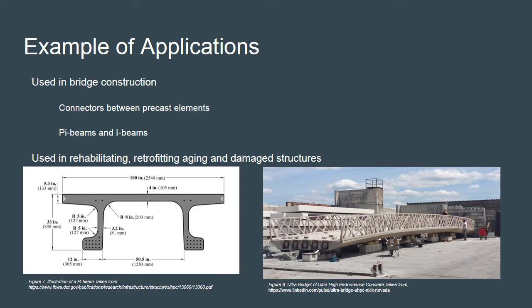The United States Federal Highway Administration released a report in 2011 detailing some of the uses of UHPC in the US. UHPC has already been used in several highway bridge construction projects. Two projects used UHPC in precast concrete girders in place of conventional concrete, where tensile properties were significant enough for the bridge to be designed without steel shear reinforcement. Two bridges in New York were built with UHPC acting as a connector between precast elements. Several pedestrian bridges around the world, including one in Sherbrooke, Quebec, have been built with UHPC slab decks. There are also wide-ranging applications in rehabilitating bridge structures, seismic retrofitting, repairing deteriorating bridge decks, and precast piles and bridge piers.